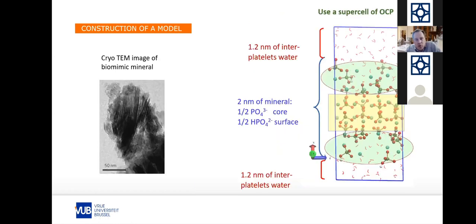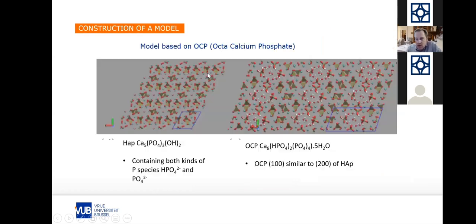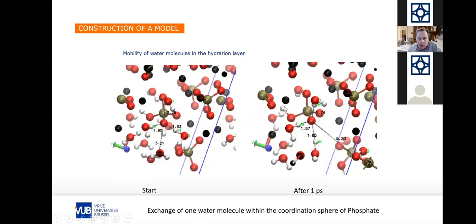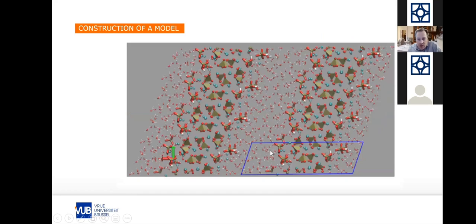And this is what we have done. So we made a model, we make our surfaces, we introduce water, we equilibrate with the surface, and we start to see what happens. Again, we can compare it with the systems that we made. Remember, these are synthetic calcium phosphate structures with these layered structures, with nanometers in between. And we did it the same. So we tried to find out the effect of amorphization at the interface with water. You see, we have the water interface, and we can see in this part how the structure evolves. So this is the water interface study.